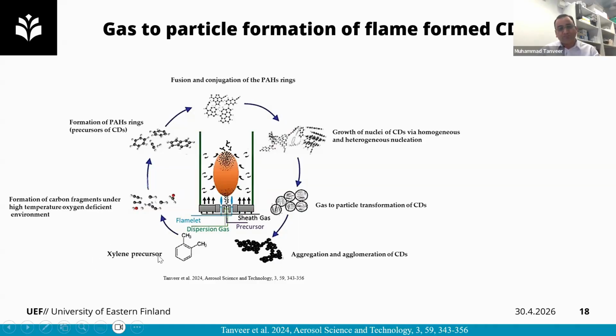So when this xylene precursor is exposed to high temperature and an oxygen-deficient environment, it produces carbon fragments in the long-chain or straight-chain form. In the following stage, these carbon fragments start to fuse together and form PAH rings, polyaromatic hydrocarbon rings. They act as a precursor for the carbon dots (CDs). And downstream of the flame, these PAHs start to fuse and conjugate together and form larger clusters of PAHs.